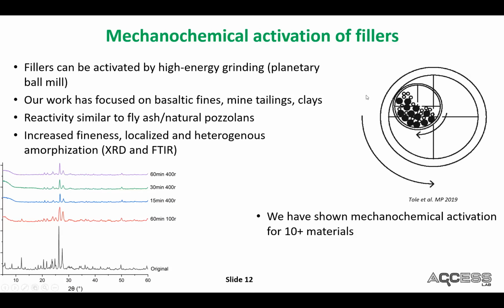Here, the phenomenology is a little bit different. We get increased fineness, and we also get amorphization. But this amorphization seems to be very different from the bulk melting case, where it only really seems to be at the surface - but also it seems to be very, very phase specific.